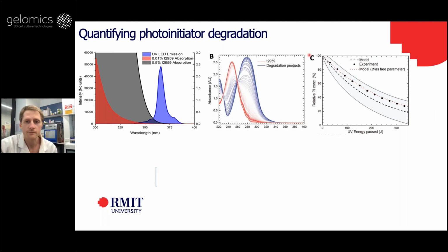Then we set up another experiment where, to really understand what's going on when the light hits the photoinitiator, we can repeatedly expose the photoinitiator solution to the same light source we've characterized, and we can monitor the degradation of that photoinitiator as it changes from the red curve, which is the original initiator, to the blue, which is the degradation byproduct after it's been cleaved.